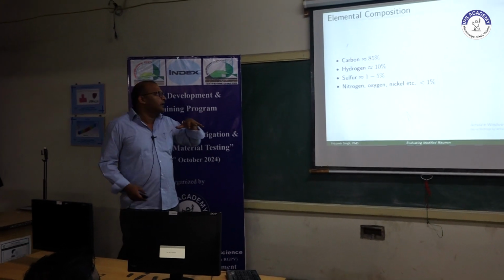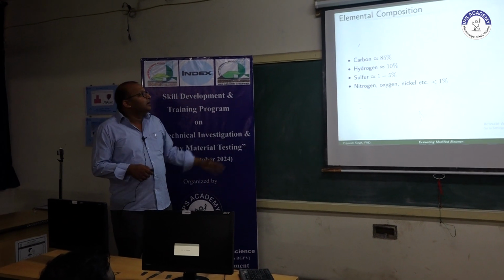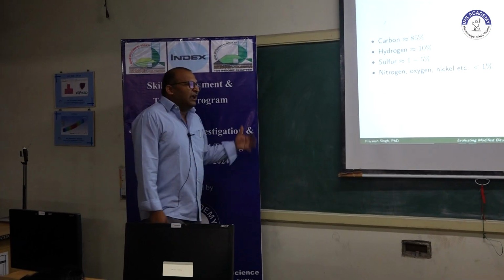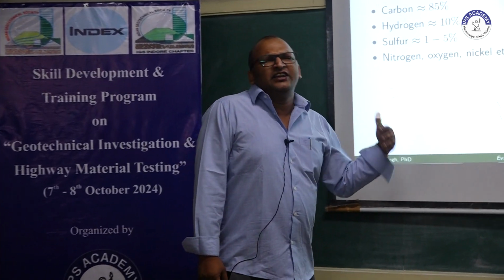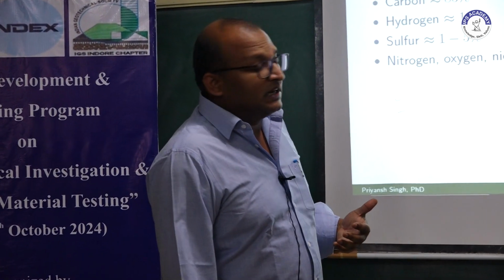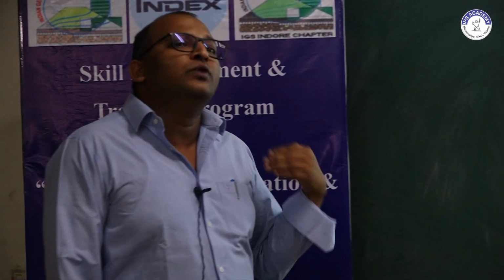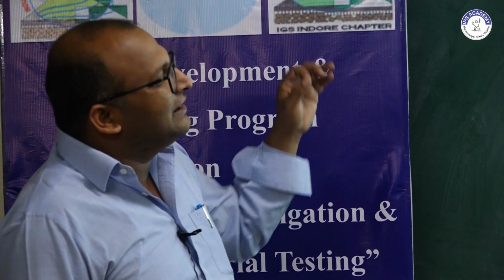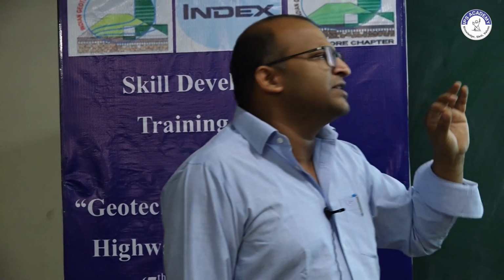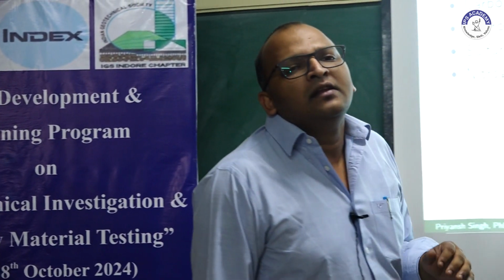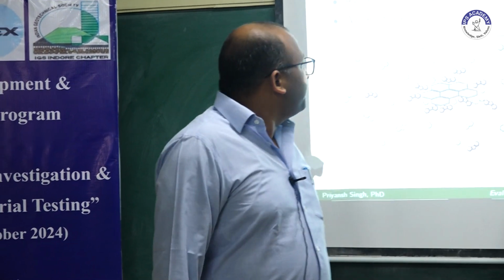Mostly, if you see the chemical composition of your bitumen, it is mostly carbon, around 70 to 85%. The next major component is hydrogen, then sulfur, and then some traces of nitrogen, oxygen, nickel or some other materials.